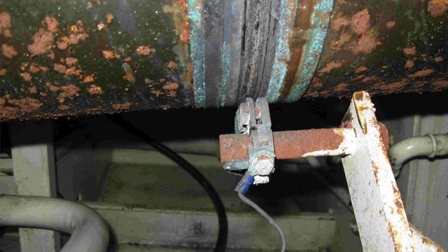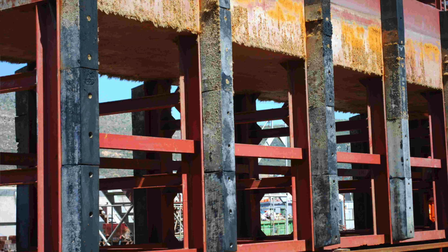But it is interesting to see how, from the Navy perspective, there's this need to protect our assets as we absolutely should. And it's encouraging to hear that there are cathodic protection. And obviously, the photographs that we saw, the coating. And we must never forget that the coatings that they choose are the first line of defense against the corrosion, that they provide that barrier. And in dry dock, of course, you get to the point where they're replacing the coating first and foremost, and then just using the anodes to protect the little holidays or defects that occur in the coated surface.